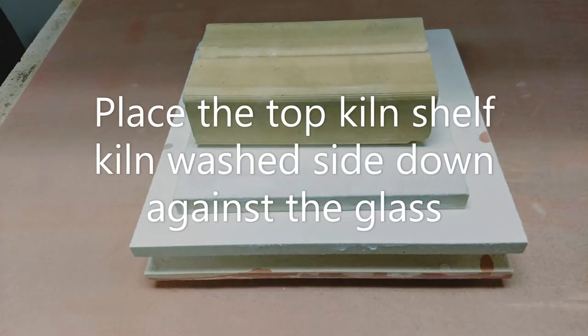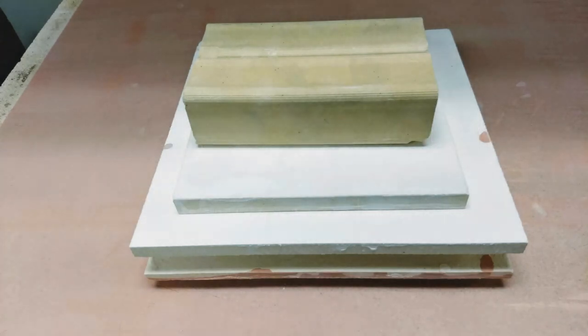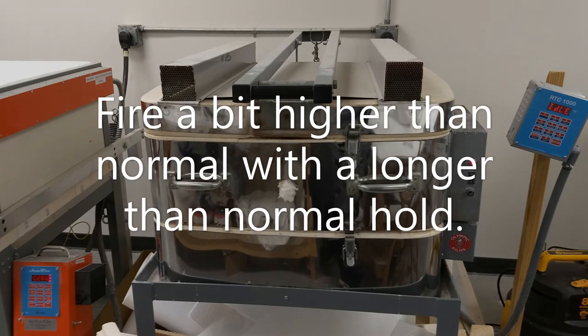The next step is to place the squares in the kiln, weigh them down with a second kiln shelf, and add some more shelves or posts. Then fire. When firing, we must be careful to go slow enough to minimize temperature variations between the glass and the kiln shelves. Because of the amount of shelf and post material in the kiln, it will take longer than normal for the piece to cool.